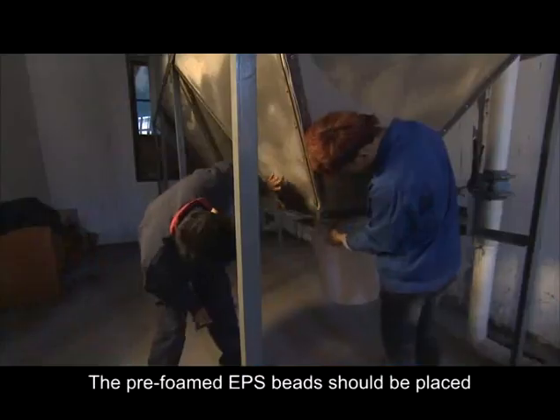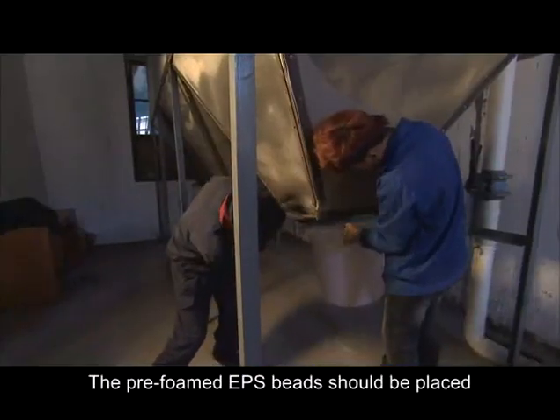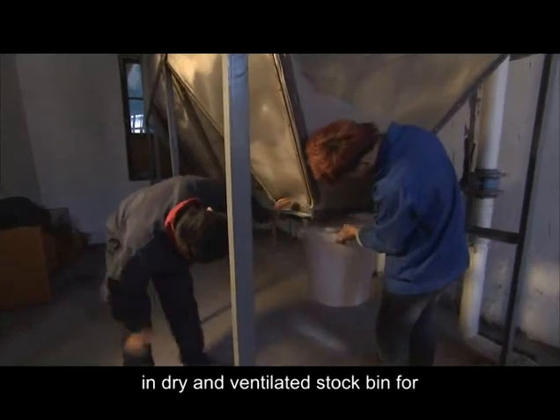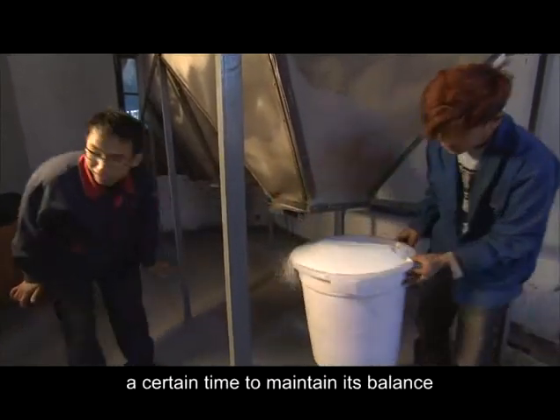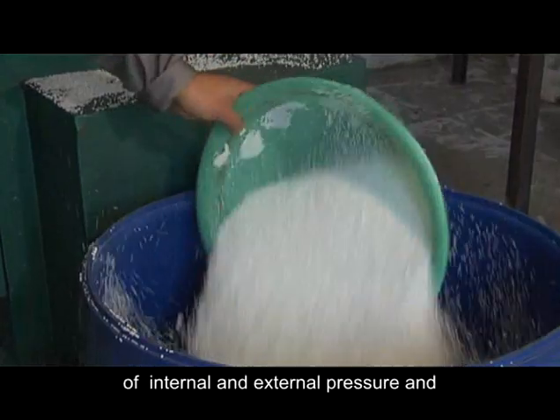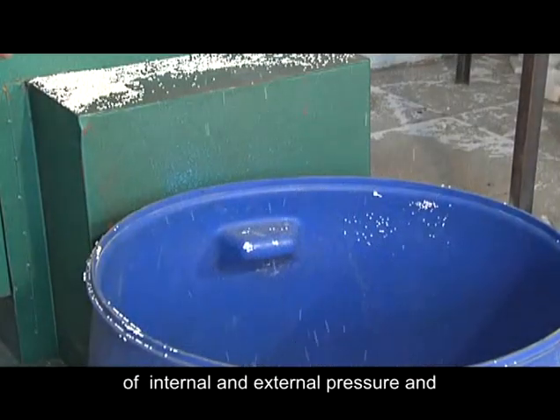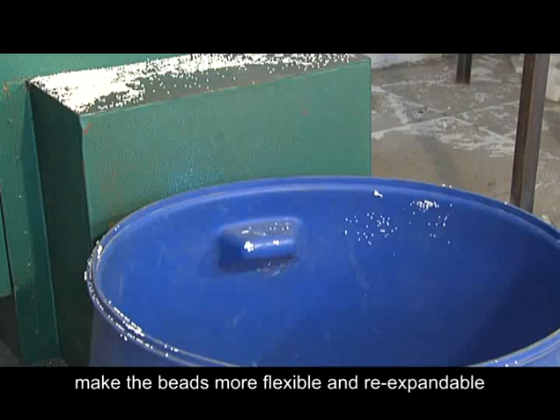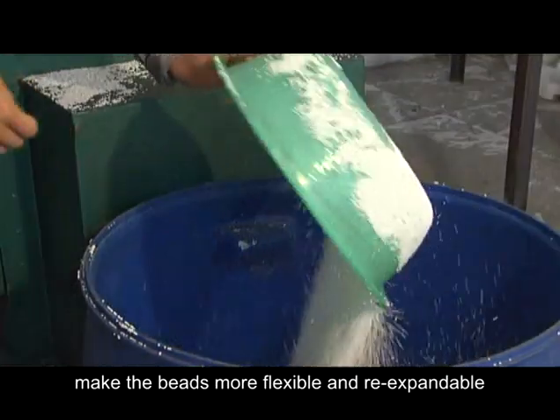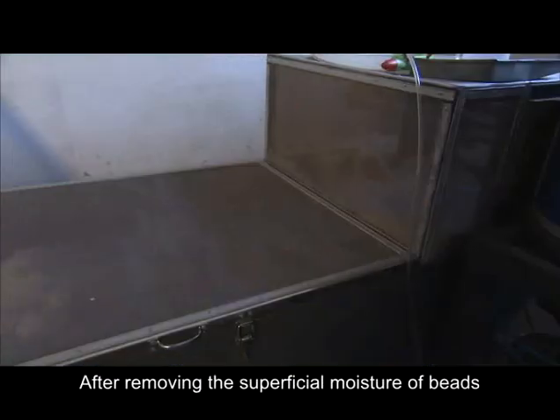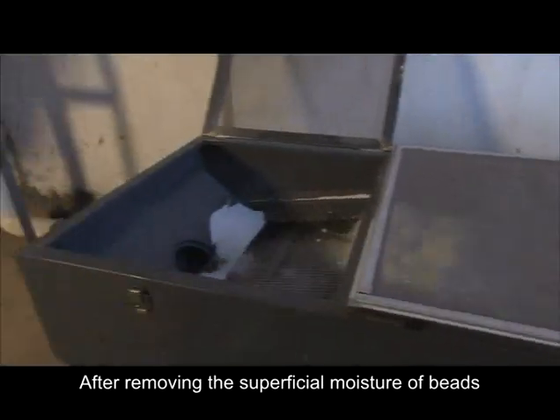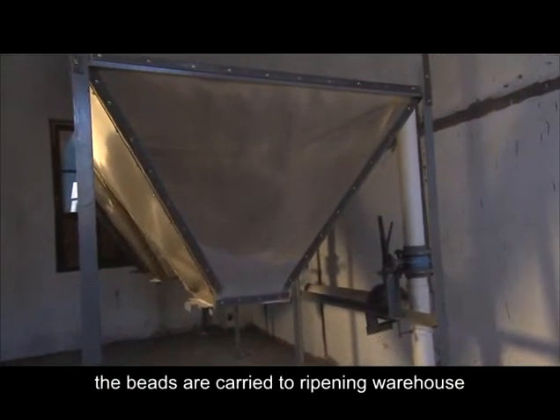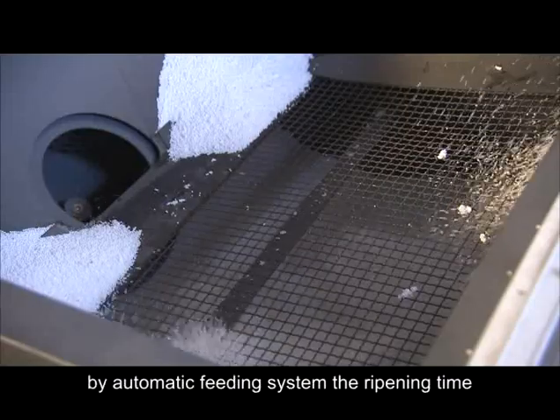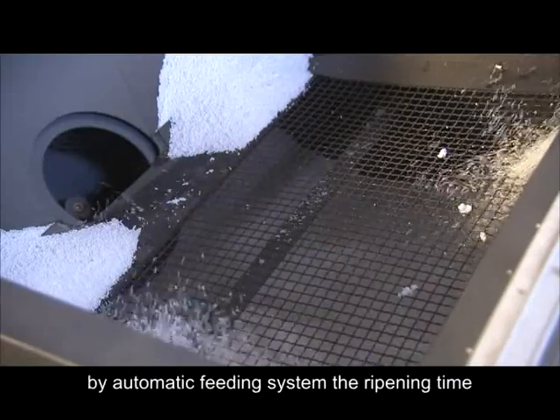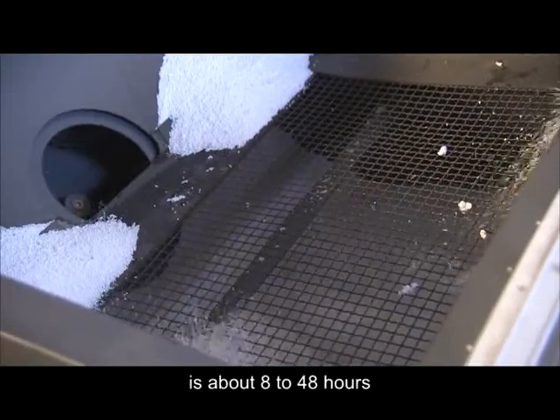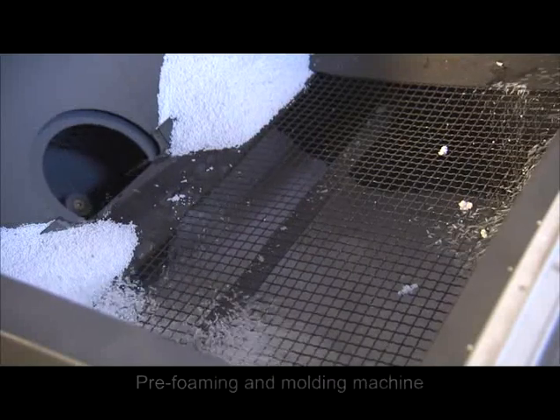Ripening. The pre-foamed beads should be placed in the dry and ventilated stock bin for a certain time to maintain the balance of the bead's internal and external pressure and to make the beads have flexibility and re-expanding capacity. After removing the superficial moisture of beads, the beads are carried to the ripening warehouse by automatic feeding system. The ripening time is about 8 to 48 hours.